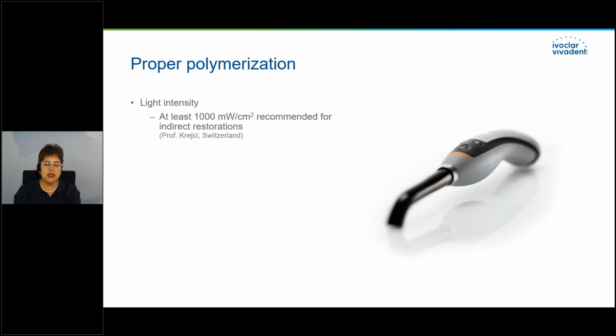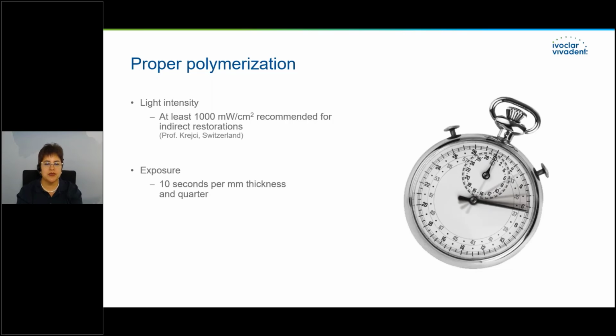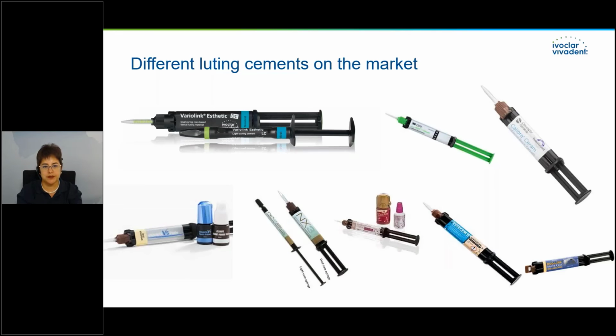How long should we light cure the restoration? Ivoclar Vivadent recommends light curing 10 seconds per millimeter thickness. As you saw in a previous study, the thickness of the restoration can influence the light transmission. If you have a thicker restoration, you have to increase the curing time accordingly. It is not possible to overcure. So if you are not sure, you are always safe with a higher polymerization time.